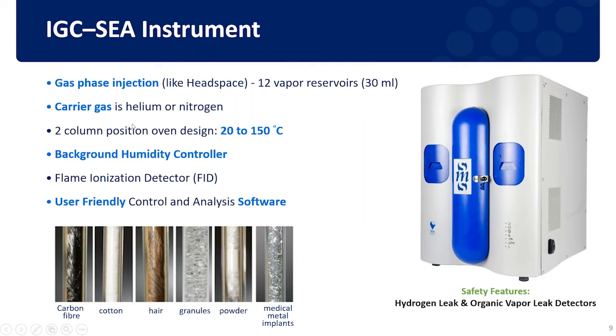So the carrier gas for the system is either helium or nitrogen. And there is a very useful function with the background humidity controller inside the system that we can also use to study the humidity effect on those surface properties of the material. The detector for the system is the flame ionization detector. The FID is really sensitive to the organic vapors.